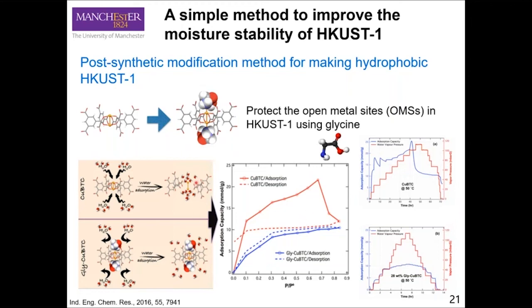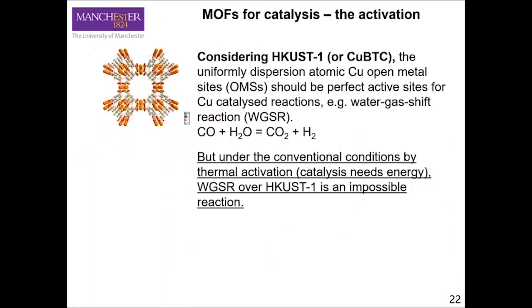And the other idea that this water vapor absorption inspired is, as you can see, the whole framework has highly dispersed copper metal sites, and they are not saturated. That's the reason they are highly selective to bind polar molecules. If they like water very much, and they are copper as well, intrinsically I think they should be very good water gas shift reaction catalysts, because low temperature water gas shift just uses a copper catalyst, and the reaction involves CO2. So the site combined with water should be a very good catalyst.